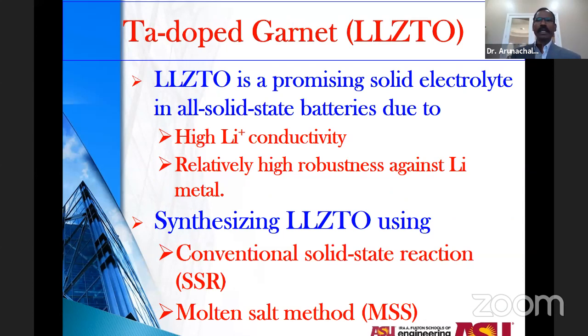Okay, so this is exactly what we did. I have a few slides to show our recent results on tantalum doped garnet structure. We already know that this material is known to show higher conductivity and also high robustness, and stability with solid electrodes is also known to be better. What we did was synthesize these materials by 2 different methods to identify which one is going to be more commercially viable, and also try different media or different crucibles for sintering them to have a stable structure. One method is the traditional solid-state reaction, and another one is molten salt.